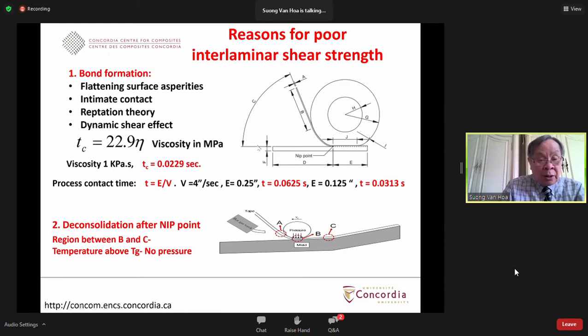Now the second reason is deconsolidation after the nip point. Here you have the roller that is pressing the layer down. Afterward the roller moves forward and you have the region behind the nip point, the region between B and C. Now it depends on the temperature of the piece in this region. If the temperature here is more than the glass transition temperature of the resin, then due to the springiness of the fibers, it tends to deconsolidate. And when it deconsolidates, certainly it affects the interlaminar shear strength.